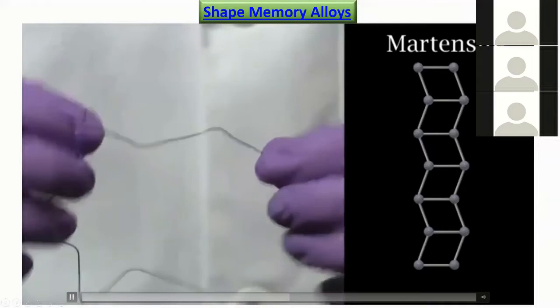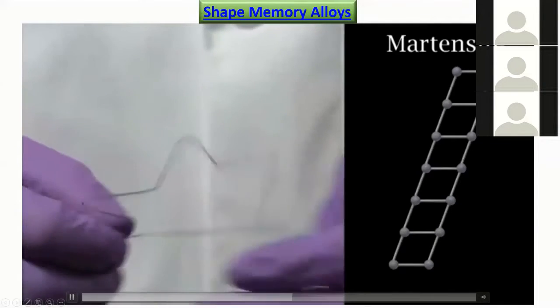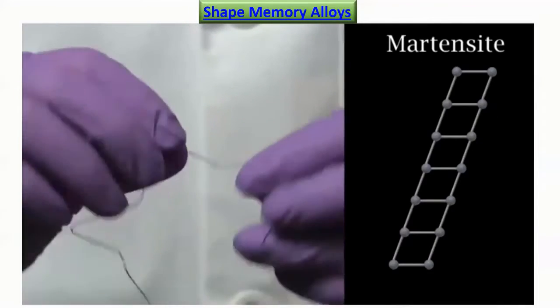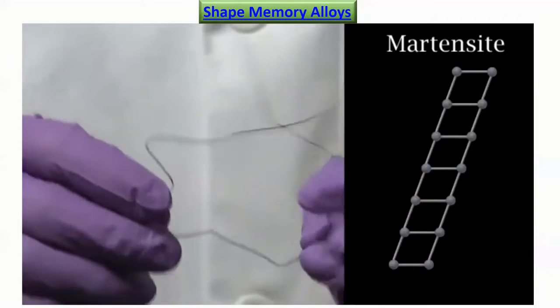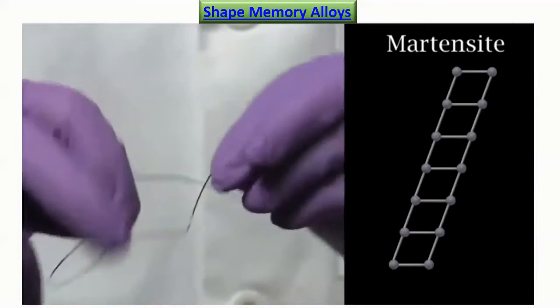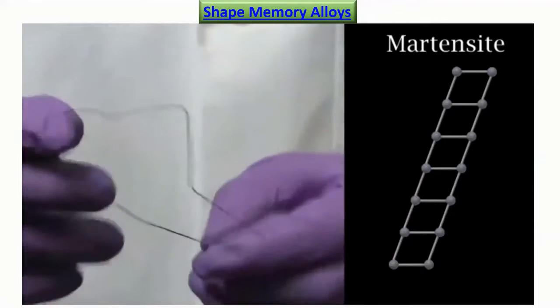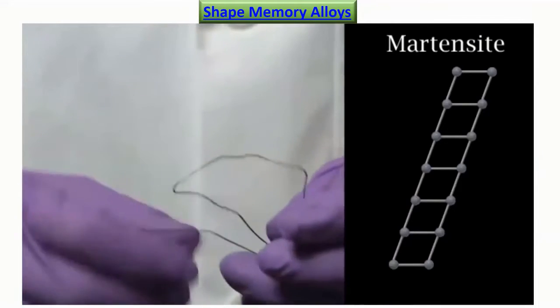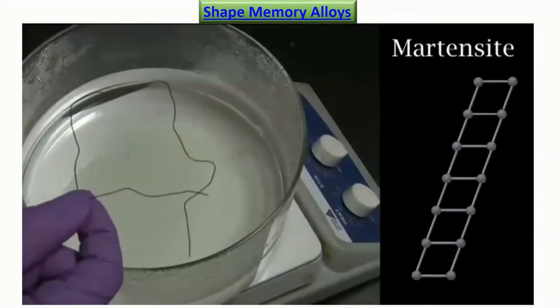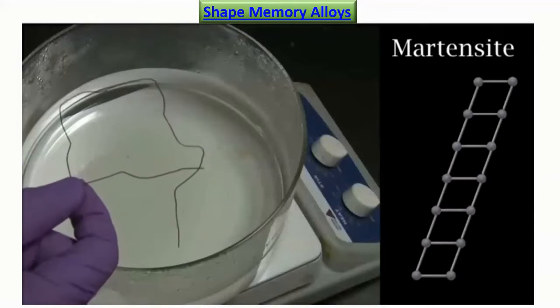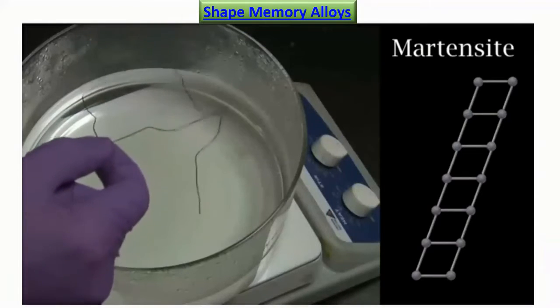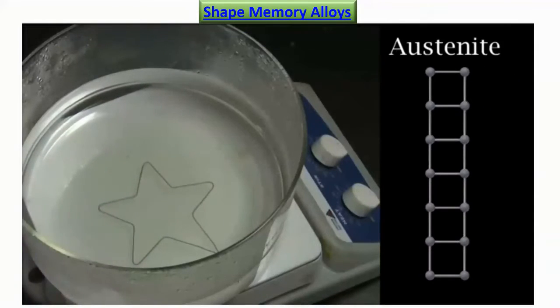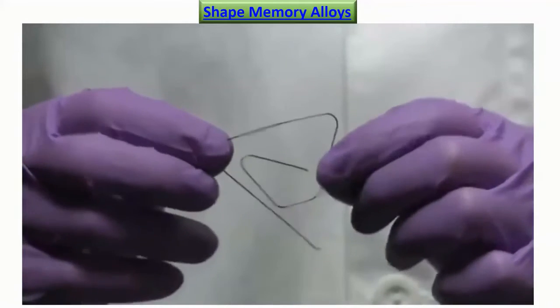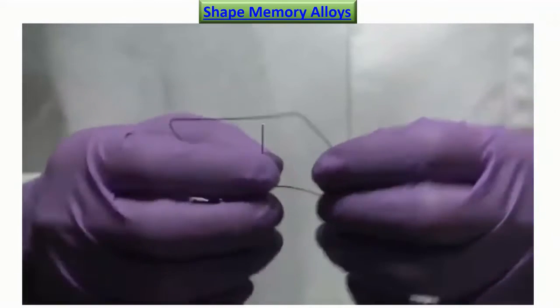does not change. Now we can bend the wire however we like. The material does not change phase, but the alignment pattern changes slightly, so that they align in one direction. This results in a permanent shape change. Now, if we heat up the wire, it goes through the phase change from martensite to austenite and it returns back to its original shape. We can repeat this for almost any shape we want.